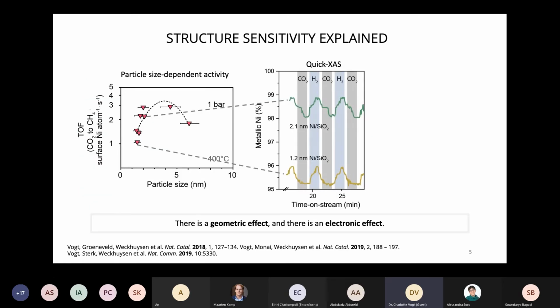And we studied different kinds of structure sensitive reactions. Here we show the structure sensitivity of CO2 hydrogenation. We show that it changes with catalyst particle size. So that means it's a structure sensitive reaction. The turnover frequency, the surface normalized activity, has a maximum at about 3 nanometers. So that was nice. We were able to use those catalyst nanoparticles to show that CO2 hydrogenation is a structure sensitive reaction. And then we did extensive operando spectroscopic studies to explain why.